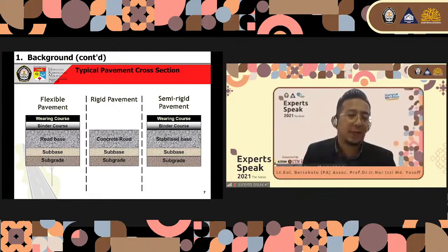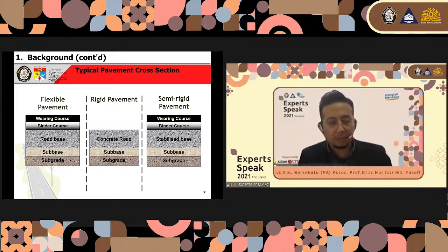Normally, the flexible pavement on the left side consists of 5 layers. The bottom one is the compacted subgrade, which is around 150 to 300 millimeter. Next we have the sub base around 100 to 300 millimeter, the road base 100 to 300 millimeter, then the binder course around 50 to 100 millimeter, and the last one is the wearing course around 25 to 50 millimeter. For rigid pavement, the surface course can vary in thickness, but it is usually between 150 millimeter for light loading and 300 millimeter for heavy loads and high traffic.